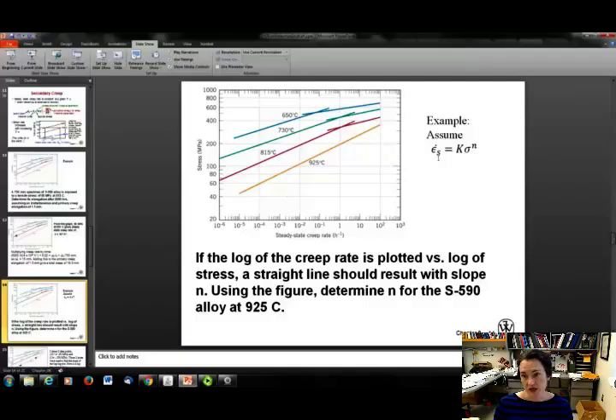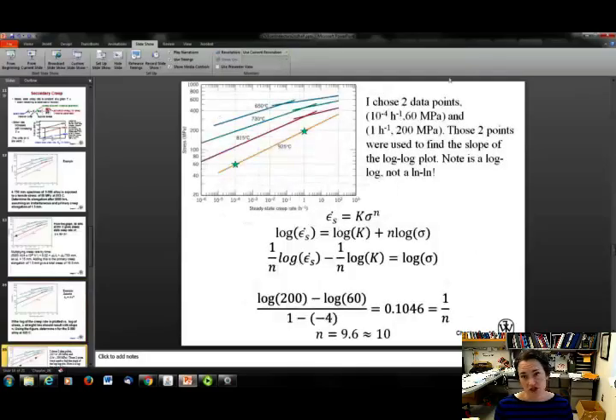So for this curve, it's just shown here, and it's some value. And so we're assuming here that epsilon dot is equal to k sigma to the n, okay? So what I'm going to do is I'm just going to choose 2 data points off this line and figure out my slope of that line, and from that I can figure out what my value of n is. So the 2 data points that I chose are the ones that kind of crossed over one of these grid lines. And so the two data points that I chose were 10 to the minus 4 and 60 megapascals. It looked like it intersected there. And 1 inverse hour, or 1 hour, and 200 megapascals. So I chose those two data points.